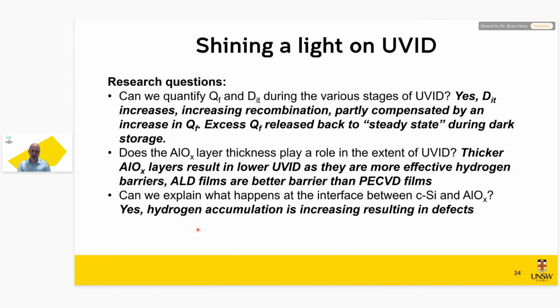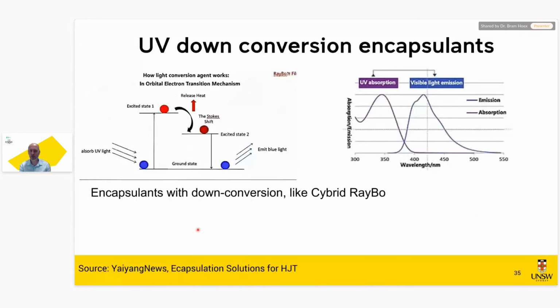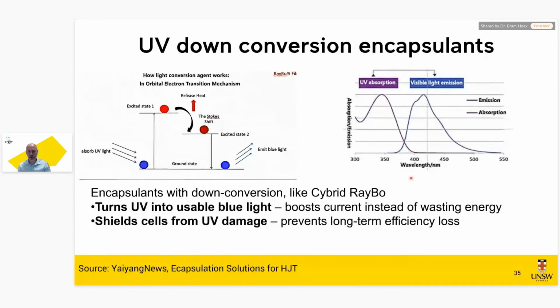So currently, I've only focused on what's happening at the cell level. Of course, quite a popular approach, particularly for heterojunction, is to use UV conversion film. So this is provided by, for example, the company Cybrid with their RayBo product, where they look at a material that absorbs UV and then emits light at a higher wavelength, so at a lower energy. So it takes it from a regime where it's harmful for the cell to a regime where the cell is not affected. And that shields the cell from the harmful wavelengths of UVID and should have improved long-term efficiency.